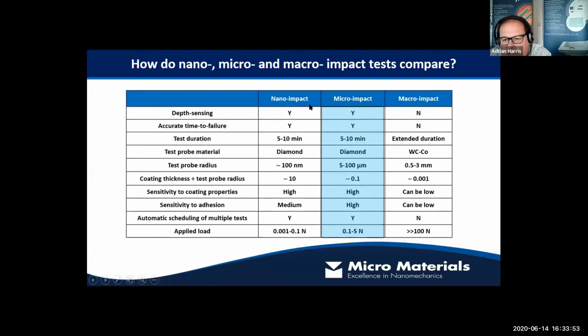So these two techniques, the nano and the micro, give us a really high sensitivity to coating properties. But as we said before, when we go to macro testing, what we find is that the stress maximum is too deep into the material. We have low sensitivity to the coating itself. Sensitivity to adhesion, as we said several times now, adhesion is a really important thing in the performance of a coated system. And if we use a probe that's too small, we have limited sensitivity to the interface. A slightly bigger probe will give us more sensitivity, but with too big a probe we have no sensitivity to the